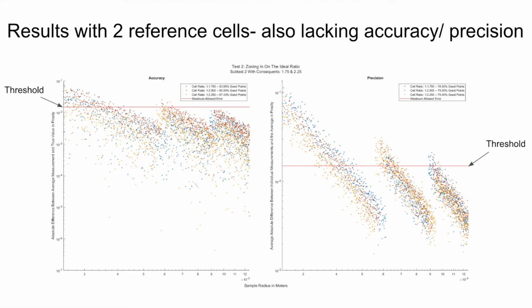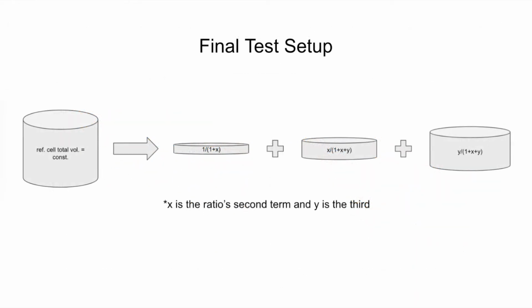The main system variable in the error analysis was the reference cell volume. In a pycnometer, the reference cell's volume should match the sample's volume. Unfortunately, this can't be done continuously, and so we had to discretize the change. The final test was with 3 reference cells forming a 1 to x to y ratio.